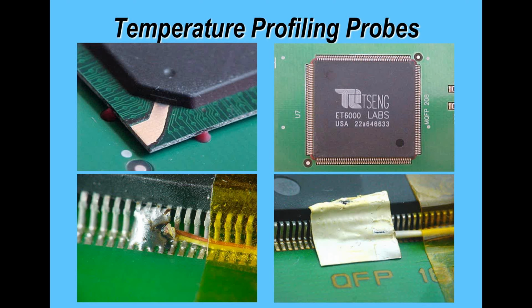Now a little bit more about profiling and mounting thermocouples. A couple of other things which most engineers have found out, but perhaps newer engineers to profiling may not have experienced so far. If you're going to be doing profiling with BGAs and you're going to be doing double-sided profiling, it's a good idea to stick the BGAs in place. So here I've just got some adhesive mounting on the four corners just to make sure the package doesn't reflow and fall off. The reason it can fall off is not to do with weight. BGAs of this type, fiberglass BGAs, will probably only be about 4 or 5 grams. But because the board may flex and the BGA may flex, the number of individual solder terminations on the bottom side may reduce because the two surfaces warp or flex against each other.